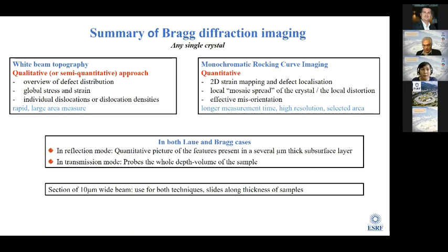Normally we start with the white beam topography first because it's really rapid. Like Julie said, it's less than 1 second for an image, and we can apply it for a large area measurement because we have a very big beam. Then we can move on to the rocking curve imaging for the selected area, where we spend longer measurement time, but keep high resolution and more quantitative results.